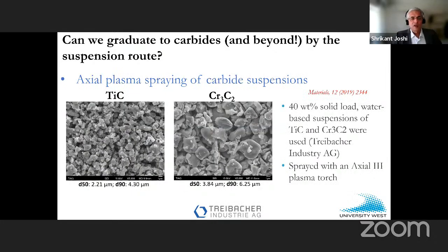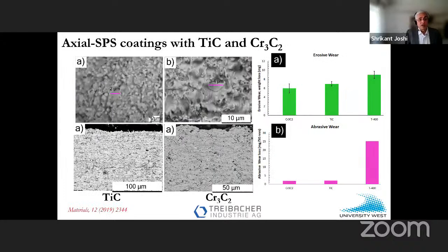Right, so alumina and chrome oxide can graduate to carbides, right? So this is kind of a one-off work, I must admit, on using titanium carbide and chrome carbide in suspension form, right? Without any binder, mind you. And we were kind of surprised to get pretty good coatings of titanium carbide and chrome carbide.